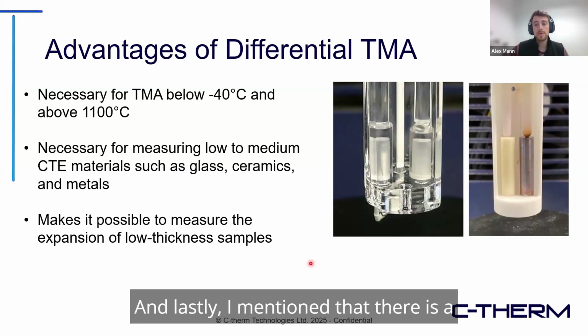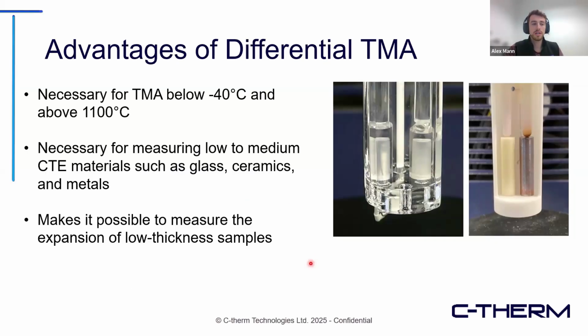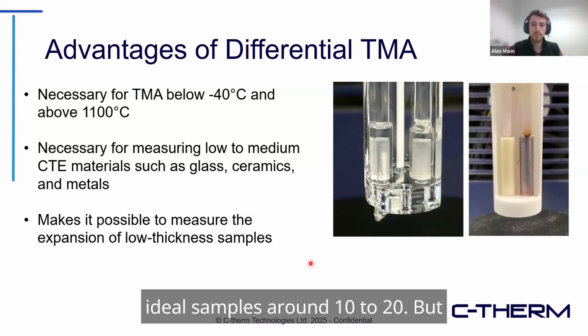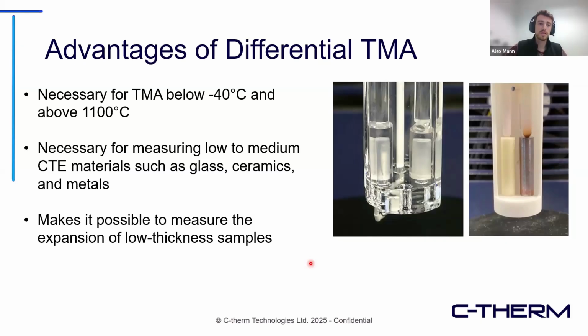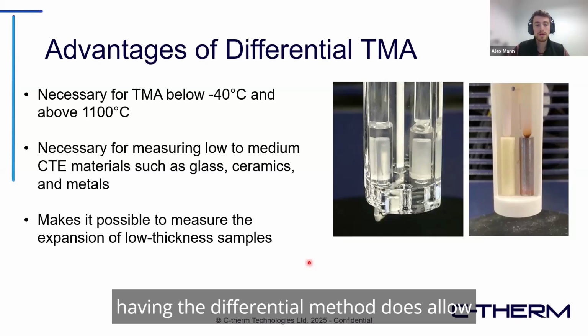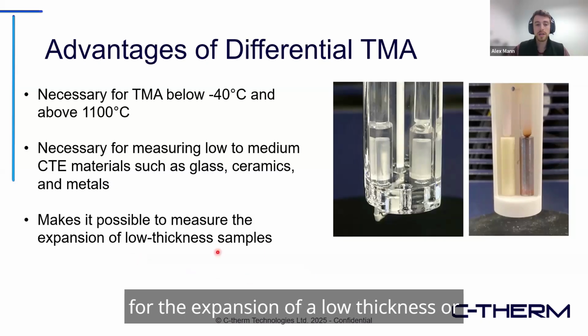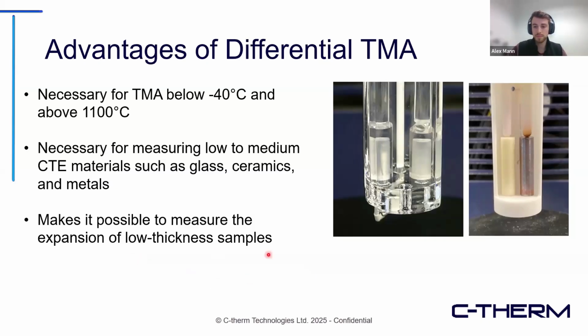And lastly, I mentioned that the ideal sample is about 10 to 20 millimeters, but sometimes that's not always possible. So having the differential method does allow for the expansion of a low thickness or low height sample.